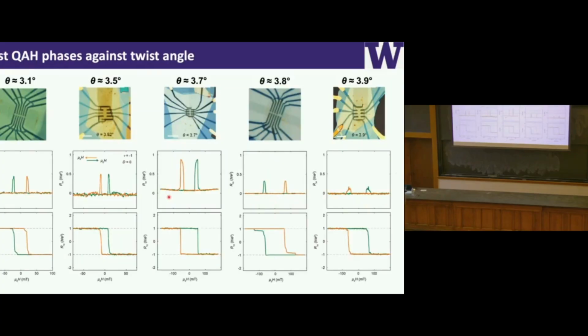All right. Last thing is about twist angle dependence. As I mentioned to you at the beginning, the effect can be seen with a wide range of twist angles. We have been seeing this effect from twist angle about 2 degrees all the way to about 4 degrees. What I show you here is quantum anomalous Hall measurements for twist angles from 3.1 to about 3.9 degrees. The middle panel is measurement of RxX, and the bottom panel is measurement of RxY. There are some detail differences, but the main feature, vanishing RxX with quantized RxY, is always preserved at zero field. So this tells you we don't need a magic angle. The effect can be seen at large twist angles, at least.